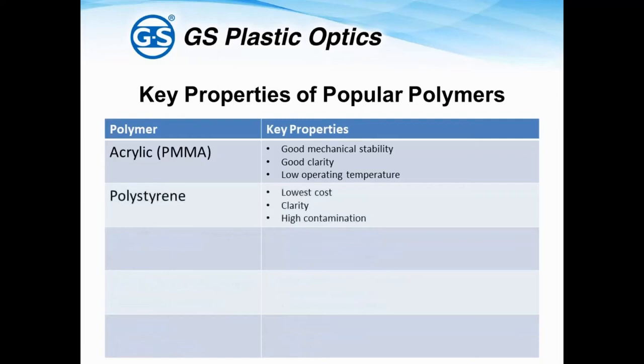Polystyrene is generally less expensive than acrylic. The material also tends to absorb somewhat in the deep blue spectrum. Polystyrene has a lowered resistance to UV and is more easily scratched than acrylic. A styrene lens, when paired with an appropriate acrylic lens, offers an effective achromatic solution. High contamination is a potential issue for molded polystyrene optics. Polycarbonate is known for its high impact resistance and the ability to perform over a wide range of temperatures. Because of its high ductility, polycarbonate optics are not easily machined. The resin is more expensive than acrylic.